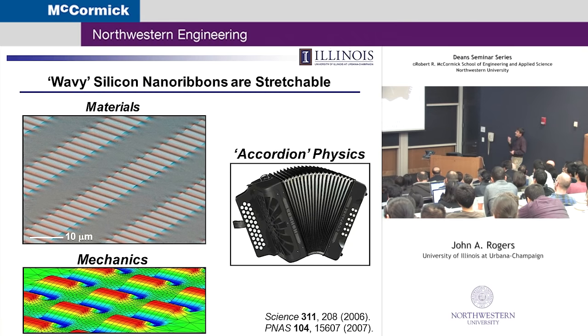And in addition, mechanics is absolutely essential to these kinds of design strategies. So you need to know the mechanics at a very, very deep level. Luckily, we've had very good collaborations with Yonggang Huang in mechanical engineering here over the years. I'm not going into the details, but we spent about a year trying to figure out the mechanics. We published a whole paper just on the mechanics of those ribbons in PNAS in 2007. So we know all of the details. And again, that's critically important for this kind of technology because mechanics design becomes almost as important as circuit design. Being able to manage the stresses and strains to afford the effective system level mechanics that you want when you're stuck with a brittle material like silicon.